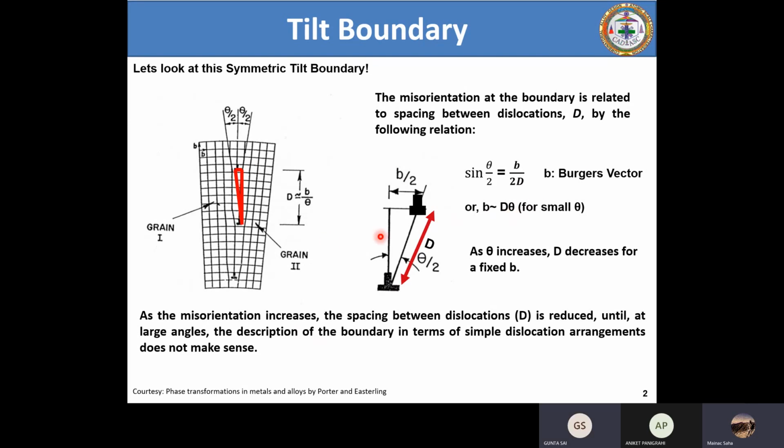This means these two dislocations are going to merge with each other. So now think what is going to be the case. If two dislocations merge because their cores are going to overlap, what is going to happen? Ultimately, this entire arrangement will be unstable. This model will again fail because visualizing a dislocation like this is not possible, because it is something which we call an instability. We cannot think of an overlap of the core of one dislocation with the core of the other dislocation. In that case, this model will again completely fail.